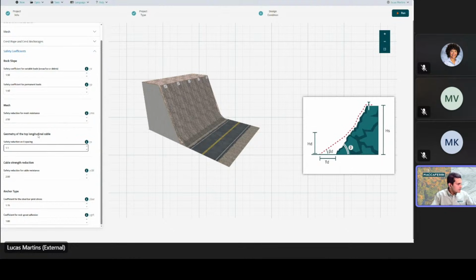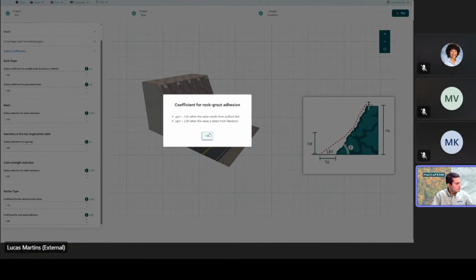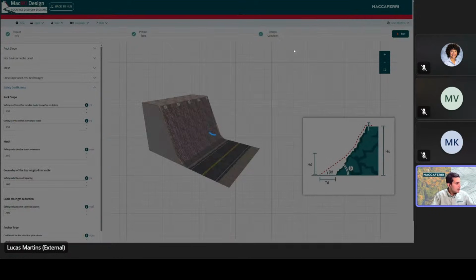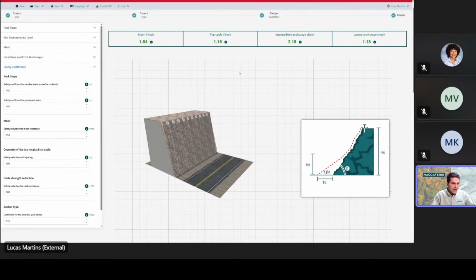You have the geometry of the top longitudinal cable. This is a safety reduction for slopes where you have a very undulated crest and you can't guarantee that your anchor spacing is going to be the 10-foot, for example, on this one that we entered. So it would be 1 for regular slopes, and then 1.1 for irregular slopes. Here you have a strength reduction on your cable, a reduction on your bar yield stress, and a reduction on that grout bond strength. All of those, if you click on the little E, there's an information. Let's go ahead and run and show you how it looks. Once you run, you're going to have those 3 checks that I covered: the mesh check, the top cable check, and the anchorage, the intermediate one, and the lateral anchorage check.